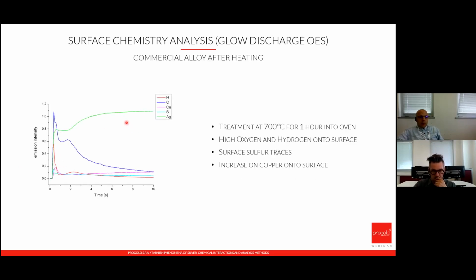And similarly to sterling silver, the commercial alloy at high temperature undergoes copper oxidation, as you can see from this relevant peak, also at the expense of silver on the surface, which is decreasing.